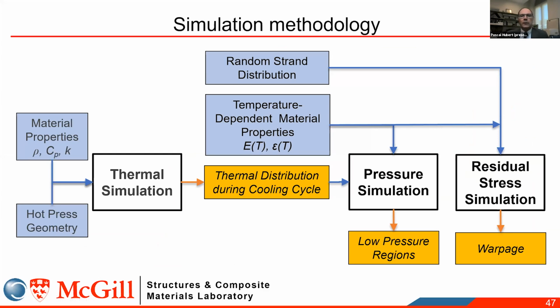So there's been a lot of work, and you've heard what was done at Purdue as well in that field. Doing simulation of those materials is key. You do the thermal simulation, so you know your temperature history, and then you can couple that with temperature-dependent properties of the material, their shrinkage, the modulus evolution, and then you can simulate how the pressure in the part changes and identify those regions of low pressure. You can also do residual stress simulation to look at parts' dimensional stability.